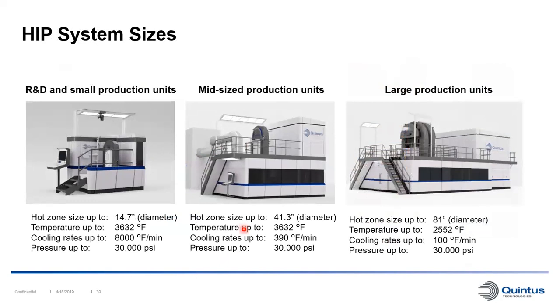Here we can see an example of the range of sizes of commercially available HIP units today. So at Quintus Technologies, we have small production units, which have diameters up to 14.7 inch, and these systems can achieve up to 8,000 Fahrenheit cooling rate per minute, which is very fast. Then we also have mid-size production units with hot zone sizes up to 41.3 inch diameters, with cooling rates up to around 390 Fahrenheit per minute.